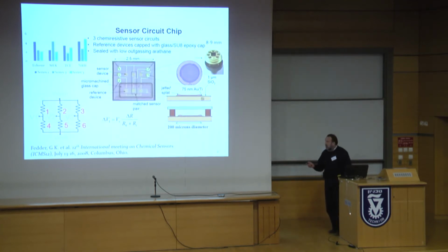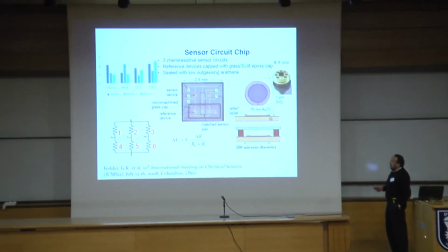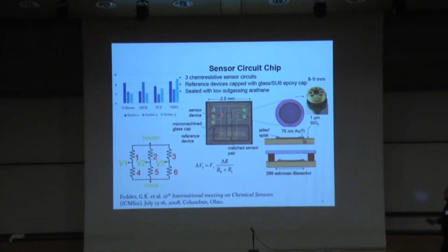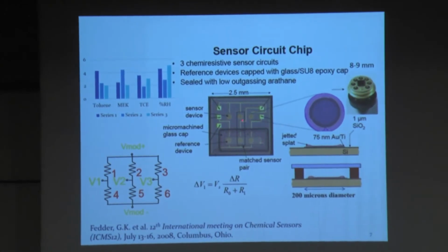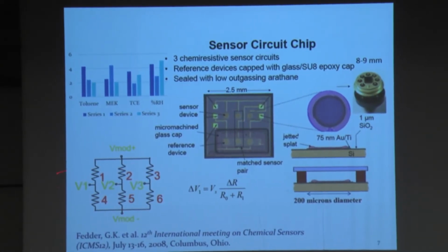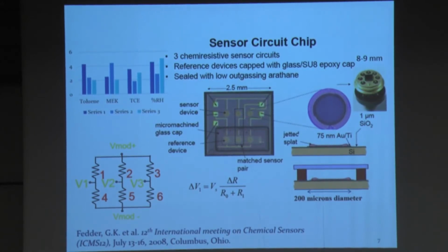The array looks like this. Look at the center. We have a silicon chip about 2.5 millimeters across, which has 6 electrodes, 1, 2, 3, 4, 5, 6, arranged in a half-bridge structure. These are matched pairs: you put the same amount of chemiresistive material on this electrode and on this one. The bottom ones get covered, so they are insulated from the chemicals, but they are exposed to temperature changes through the silicon and the header underneath. This provides temperature compensation. I should say right from the start that this temperature compensation is never perfect. You always need an additional temperature sensing device, something like a meander of gold electrodes, in order to make the fine compensation of temperature.